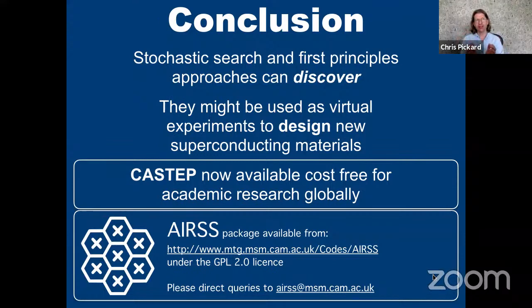The challenge is that these unconventional superconductors often seem to have more complicated crystal structures with more atoms, and also more complicated electronic structure in that they can be strongly correlated. That can be managed. I have done structure predictions for the cuprate structures. It works. I can find the structure of YBCO from first principles, no problem. The problem is that we haven't got a way of taking that crystal structure and predicting a Tc at the moment. Thank you very much for the question; it's almost like a manifesto: can we do that? If we could, it's really worth it because we could then do computational materials design. But my understanding, and I'm not an expert in unconventional superconductivity, is that that's not available at the moment.